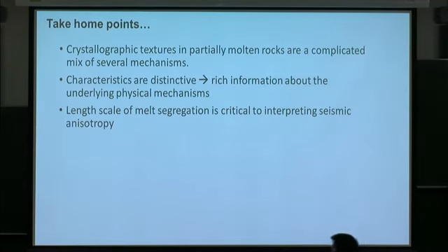Okay, so, Lars? Yes? And when you say locally high melt fractions, could you remind me how? In the bands, the melt fraction can be something like 15%. Sometimes it's higher, sometimes it's a little lower. Yeah. So I don't think you're above the rheologically critical melt fraction. I don't think you're really disaggregating, okay? But really, it's a relaxation of the compatibility constraints.